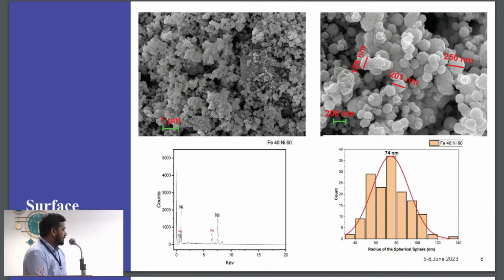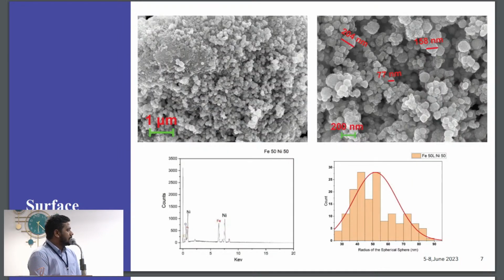This is the surface morphology of the iron 40 nickel 60 alloy. Here the first 2 images are the low resolution and high resolution SEM images. The third one is an EDAX image. In that we confirm the iron nickel composition. Slight oxygen is due to surface oxidation. And the histogram for iron 40-60, the particle size distribution curve, confirms the average radius of the spherical particles is 74, and for the case of 50-50 it is nearly 55 nanometer.